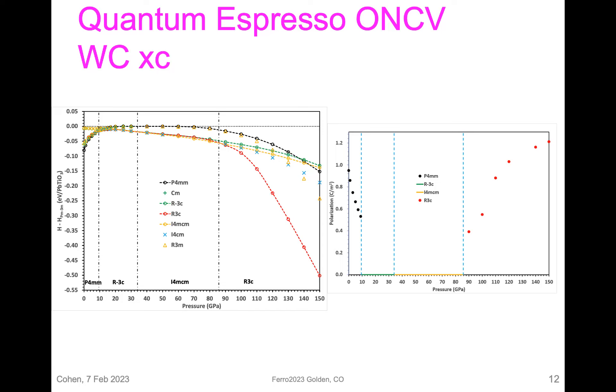We find that tetragonal lead titanate is stable up to about 10 GPa, but then it becomes R-bar-3C, which is centrosymmetric and there should be no signal. It's a first-order phase transition — not a soft mode transition — but the instability of the tetragonal phase looks like a soft mode transition. You can see from the pileup of enthalpies how close in energy all these different phases are.